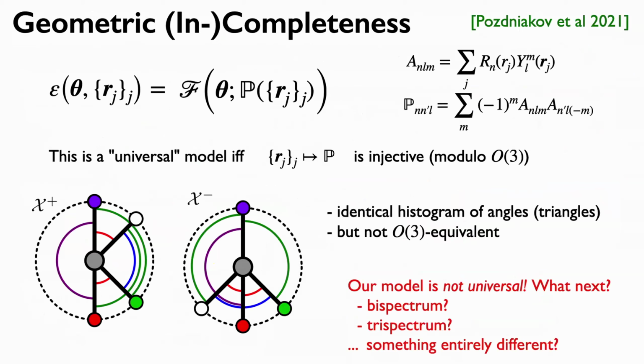But no matter how fancy the nonlinear model would be, you wouldn't be able to distinguish these pathological cases. So even if you might not use the most rich base descriptor that you like, you have confidence that you can turn the knob high enough to at least be able to distinguish the most pathological cases. The paradigm examples are the Behler-Parrinello networks and GAP-SOAP.